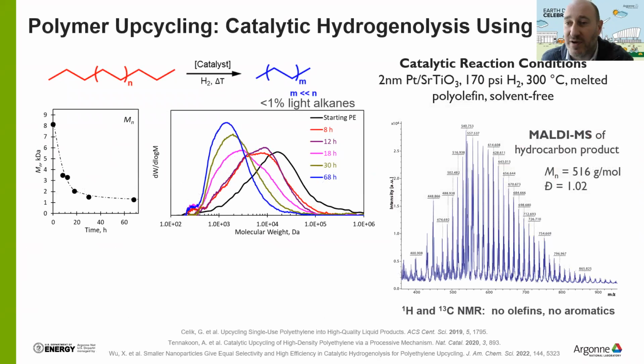What we did, and it was very, very interesting, we took what we call high density polyethylene. It is a very linear polymer. It doesn't have any branching along the chain. The water jug that I showed before is made of this polyethylene. These are the conditions that we are using. Initially we used a 2 nanometer particle size, 170 psi of hydrogen, 300 degrees. There is no solvent. We are using the polyethylene melt as a medium to do this reaction in a batch system under stirring.